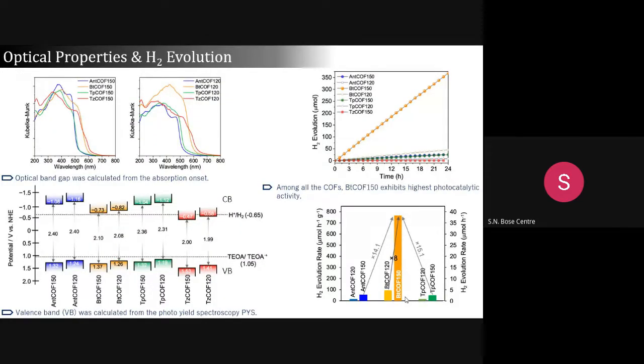Here we have analyzed the optical properties. There you can see the samples synthesized at 150 degrees and 120 degrees have almost similar band gaps, which is presented here. So this is 150 and 120, almost 2.4 eV band gap. You can see it is similar, but their band positions are slightly different from each other. In the case of the TZ sample, you can see they are well below the hydrogen reduction potential. Now, from this analysis itself, we can say this will not give any hydrogen because it doesn't have any driving force, which I was talking about. Here you have sufficient driving force, but here there is no driving force.